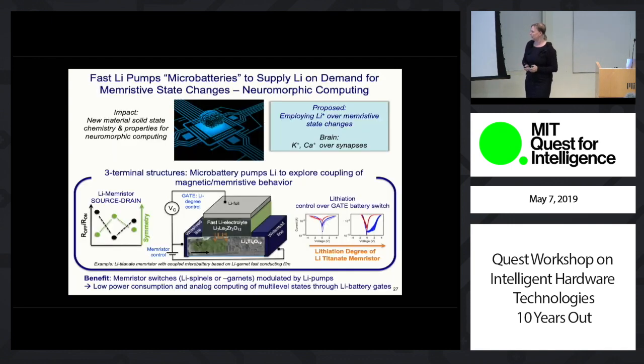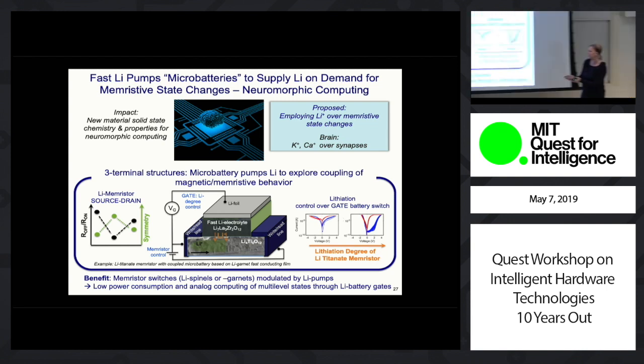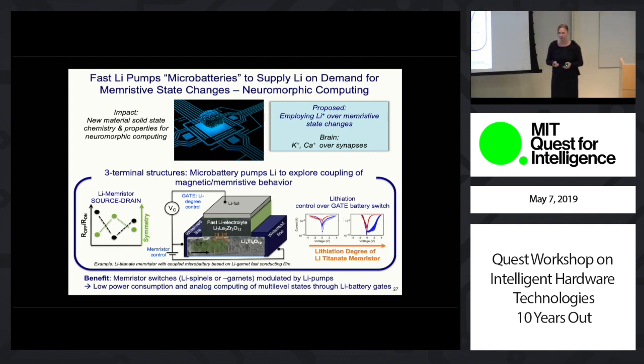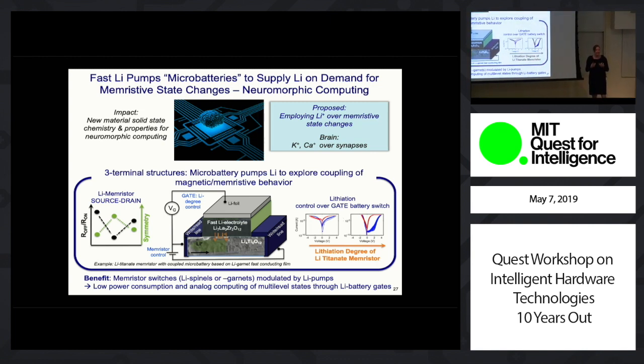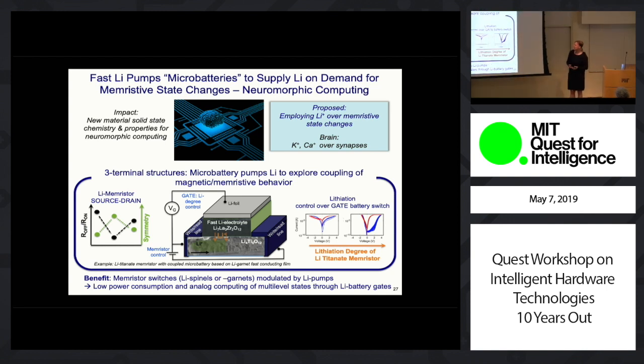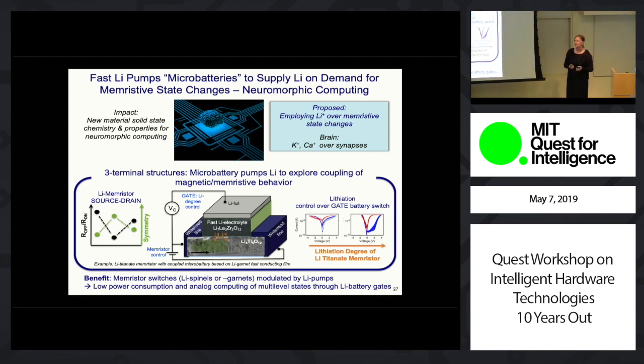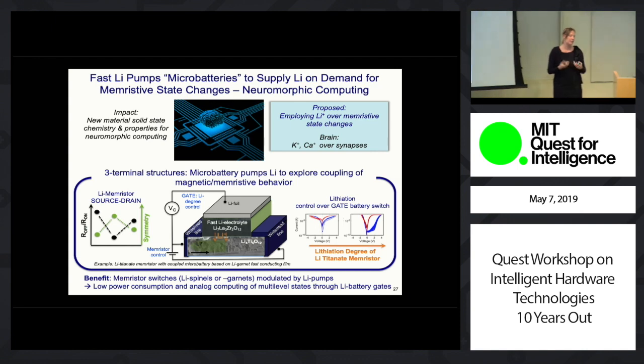So what we're currently working on is a device where we create this lithium titanate on the bottom. That's the one memristor, and it's a three-terminal device. What would be the gate in a transistor is, on top of it, a lithium-conducting electrolyte and lithium foil. That allows us, like with a micro pump, to pump lithium in and out, and we can thereby control the synaptic weight of the unit on demand. And that, I think, is a new approach that can help us actively play with the synaptic weight and add new solutions to this voltage-time dilemma.